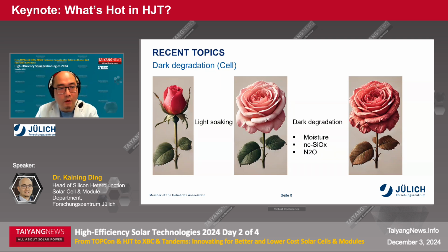So far the observations have been that if you put it in a nitrogen box, the dark degradation seems to be lower. So this indicates that the dark degradation is somehow related to the environment, like moisture. And there have also been some observations regarding the increase in the oxygen content. If you move from amorphous silicon to nanocrystalline silicon oxide, the dark degradation seems to be stronger.